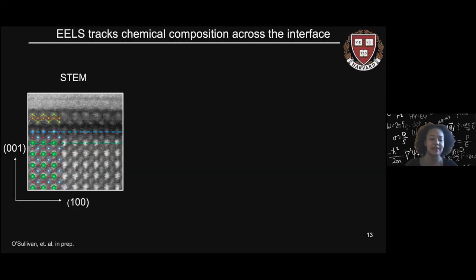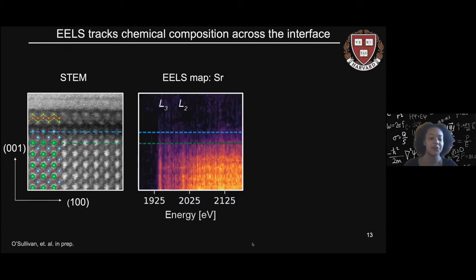So now to present these findings in conversation with our STEM measurements. Here I've presented the STEM measurements that I showed several slides ago with the crystal structure overlaid, as well as dotted green lines representing the top layer of strontium atoms and a dotted blue line representing the top layer of titanium atoms. We can then do our EELS analysis for a specific element. So here is our EELS analysis of strontium. And you can see our x-axis is now the energy lost, and our y-axis is exactly aligned with spatial resolution of our STEM image. So the blue dotted line represents the top layer of titanium atoms, and the green dotted line again represents the top layer of strontium atoms.